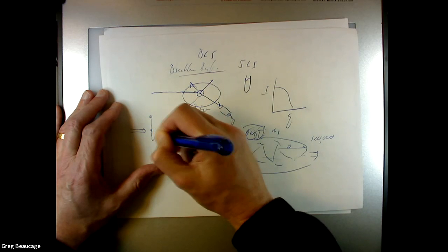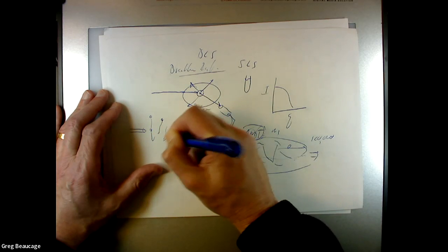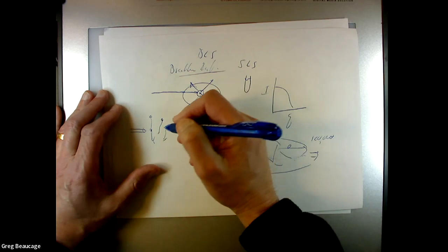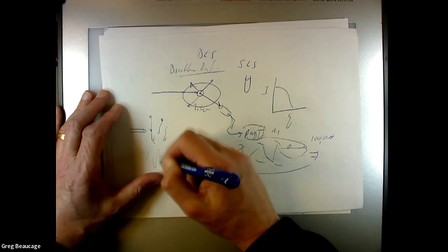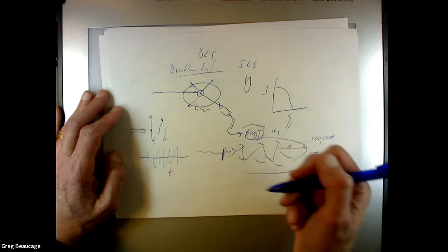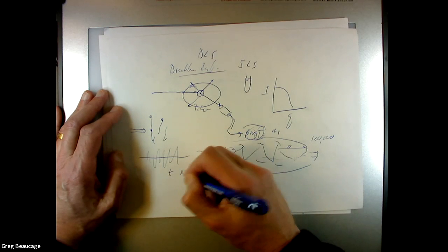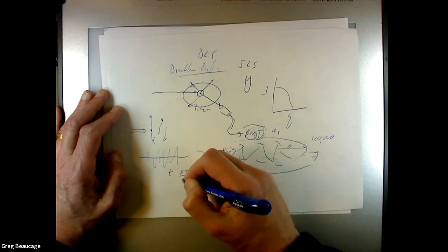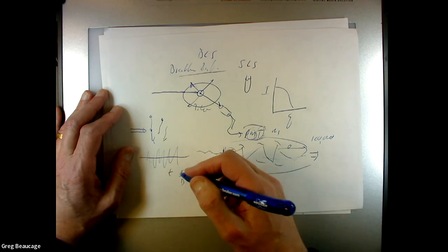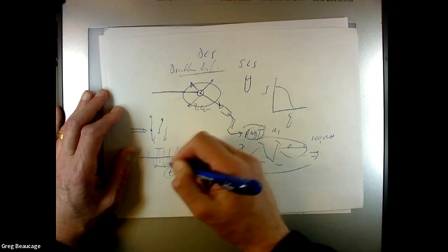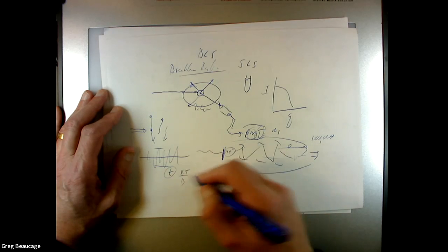Right? So you can have the signal coming off this, and if your beam comes in, and then your stuff is kind of floating around, right? So it'll go in the beam and out of the beam. So the pattern that you get from that is fluctuating in time. You get this fluctuating pattern, and the fluctuations get bigger with kT, and they get smaller with the diffusion coefficient. Right, so it's the amplitude of the fluctuations, and the time scale has to do with the distance of the thing.